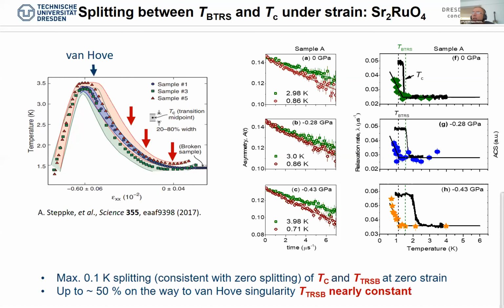Okay, on the left side, here you see first data for low strains. So here's zero strain, and then we apply some strains on this shoulder where still the TC goes up by applying strain. And here on the right side, you see the data, and you see, for example, that at zero strain, indeed, the black curve here now is an AC susceptibility measurement in situ, and the green data points are the relaxation rates in the μSR experiment. And you see that within resolution of temperature, the onset of the time reversal symmetry breaking is at TC.